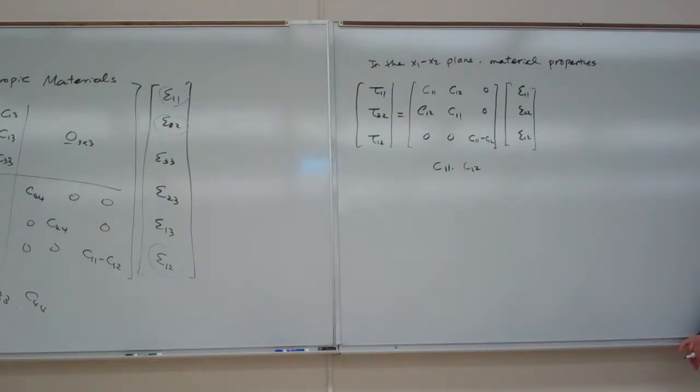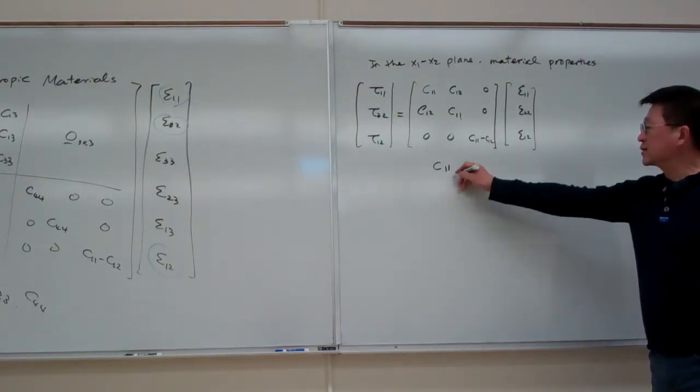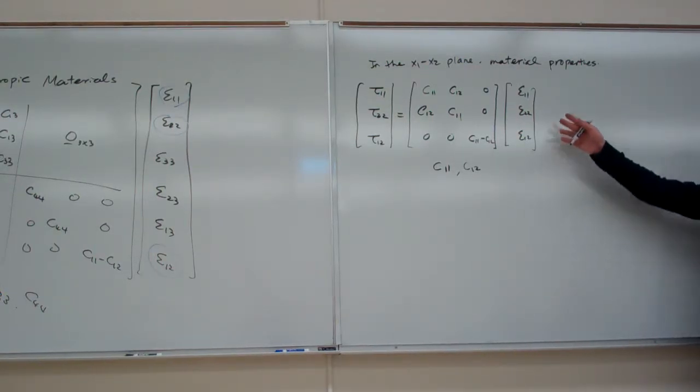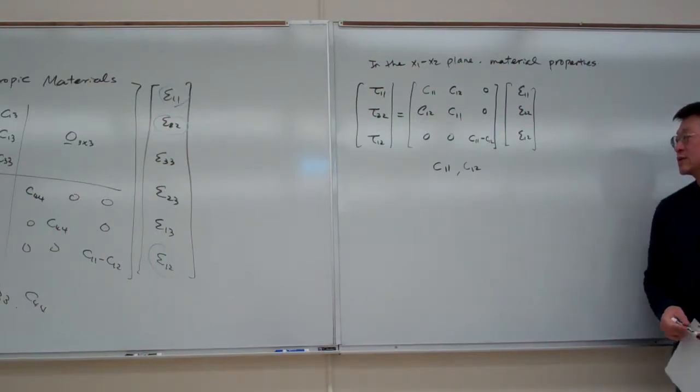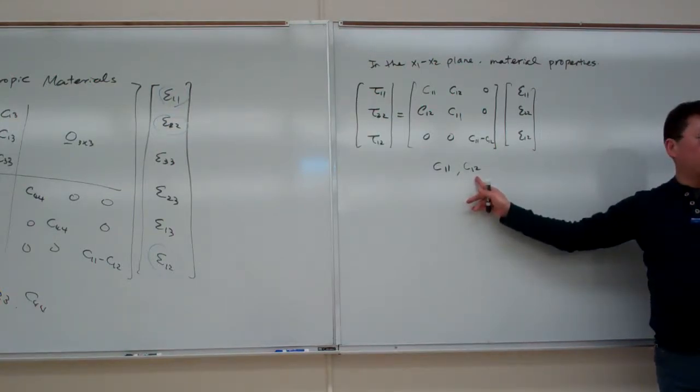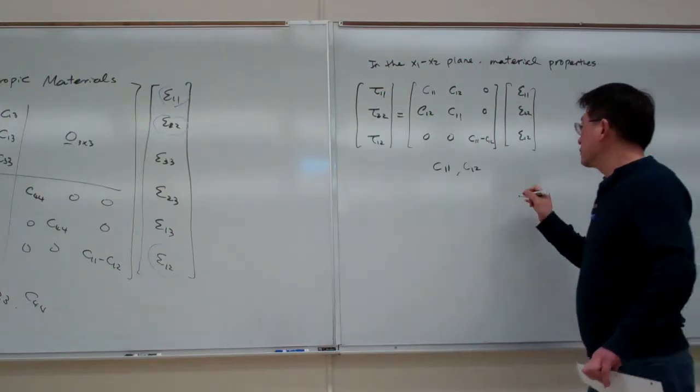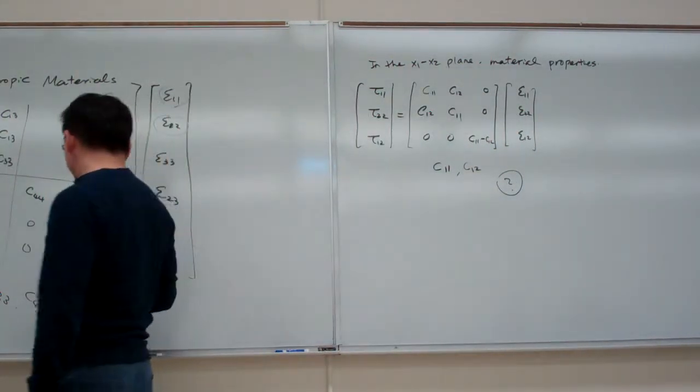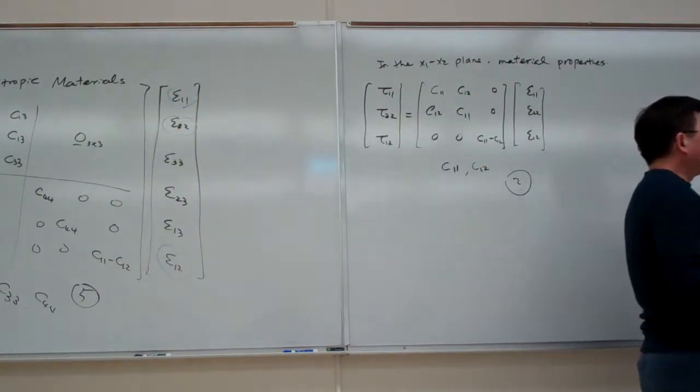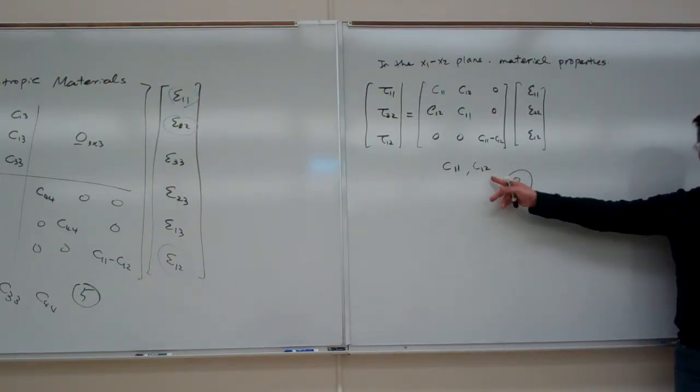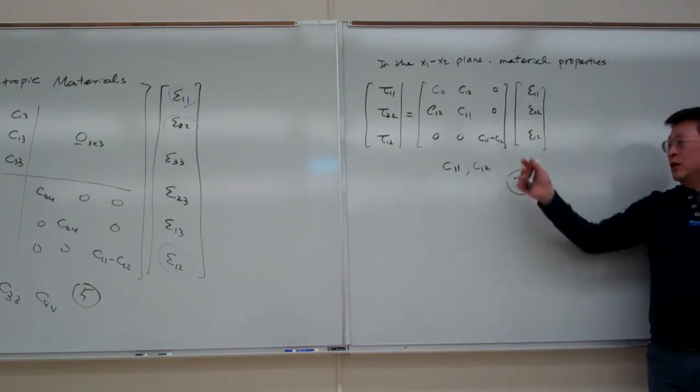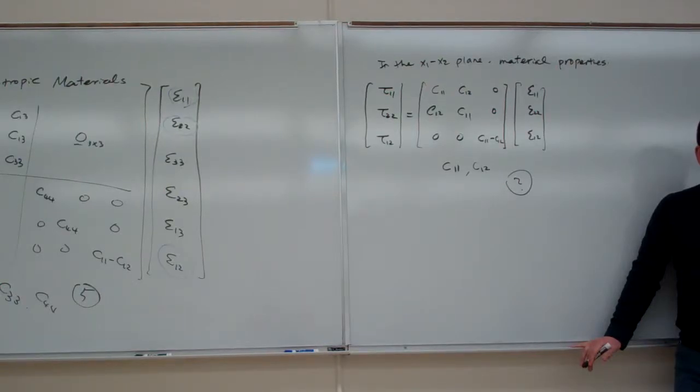So that is the first, our first taste we've been doing these work slow, stress-strain relationship for a couple weeks. Eventually, we reach the very common material properties, isotropic material properties. And for this example, I only demonstrate it's in two planes, X1, X2 planes only. But here that is, it comes to the very good, important conclusion is this. For isotropic materials, we only need two independent elastic constant. So here we have only two, and compared to transversely, this is five. So that is a very quick conclusion. We can extend it from our study here.